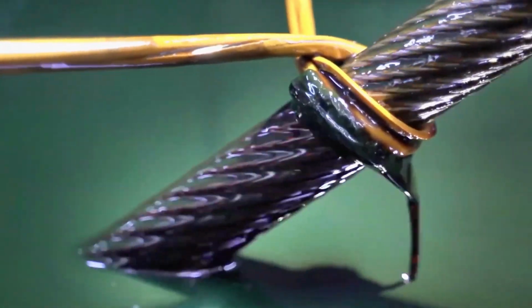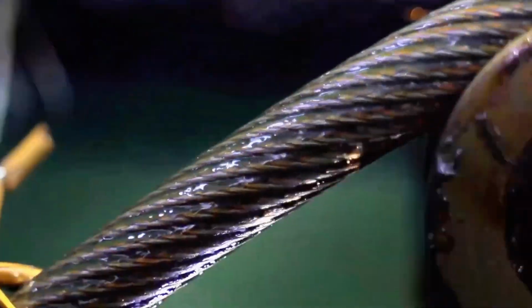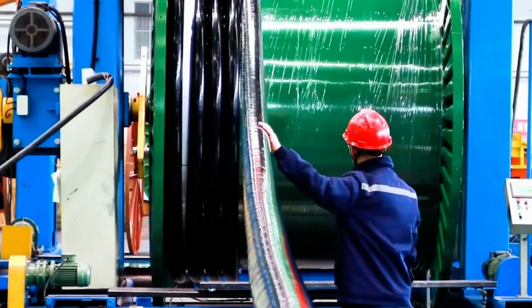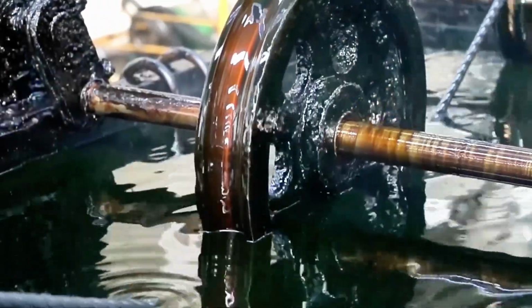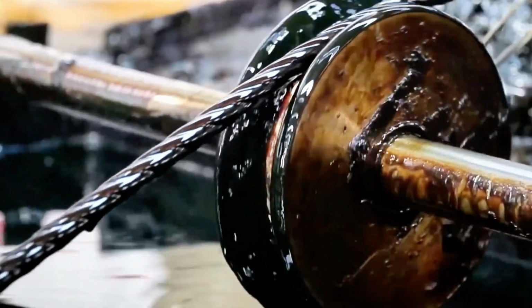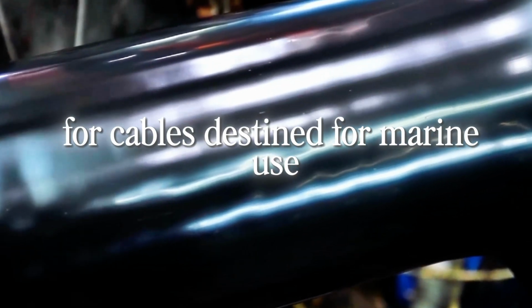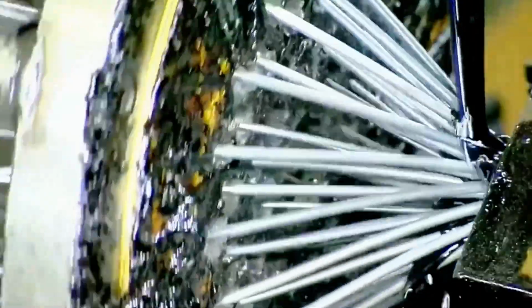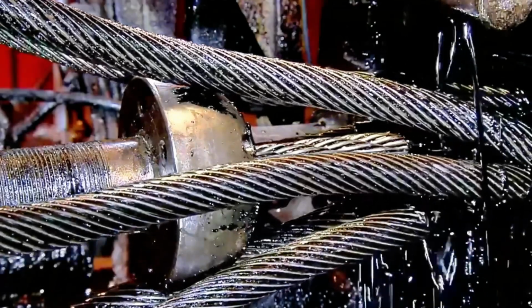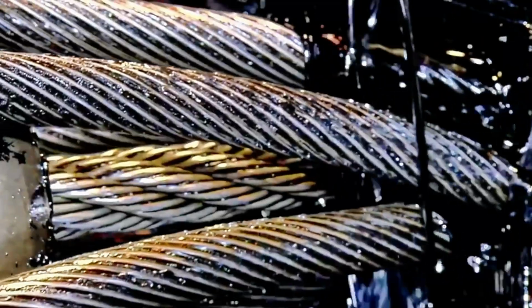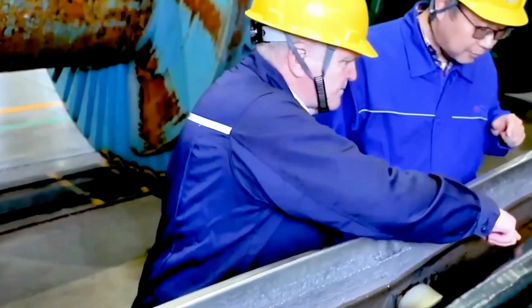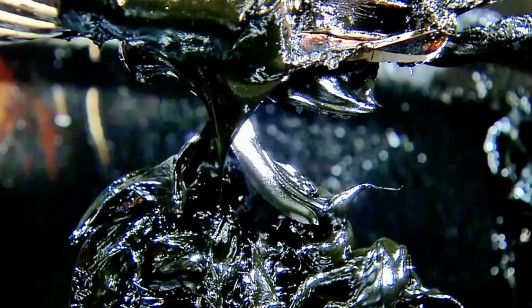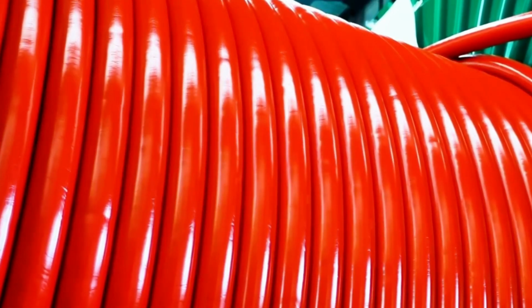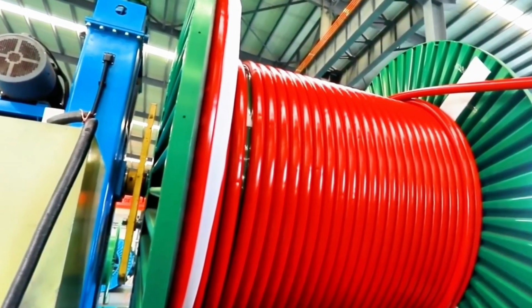the twisted wires. Some cables use synthetic oils with antioxidation additives. Others are treated with specialized greases containing corrosion inhibitors and water-repelling compounds. For cables destined for marine use, such as deep-sea mooring lines, extra compounds are added to prevent electrochemical corrosion from saltwater exposure. Flow meters, temperature gauges, and pressure sensors make sure the application is perfectly uniform. Too much oil can cause slippage. Too little leaves the steel unprotected. It's a delicate balance that ensures the cable can flex, twist, and endure decades of constant movement without internal wear.